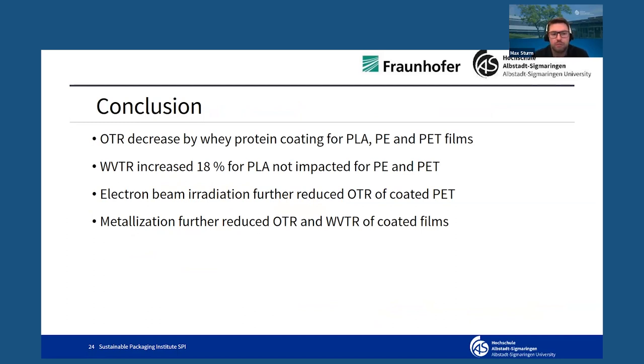With the electron beam irradiation, we were able to further reduce the OTR of the whey protein coated PET. And with metallization, the OTR and water vapor transmission rate were further decreased, also enabling high barrier applications concerning the oxygen transmission rate with these films.